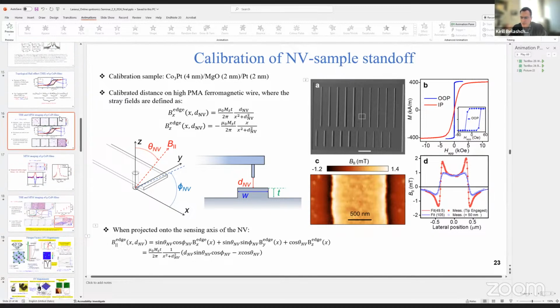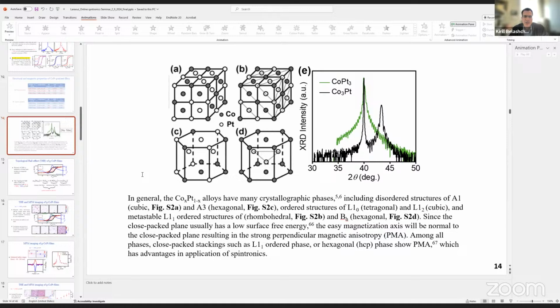For the L10, you can actually expect different ordering domains with different orientations. Yeah, in principle one needs to do further analysis. We are trying to do TEM as well, because we also need to correlate how this is ordered along the films, or just in a portion of the films. In earlier studies, they found formation of platelets. It can be a complicated microstructure, I suppose.